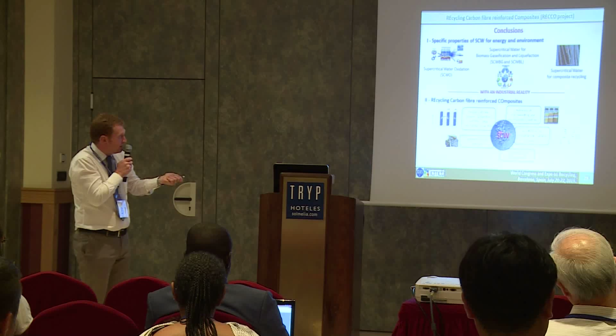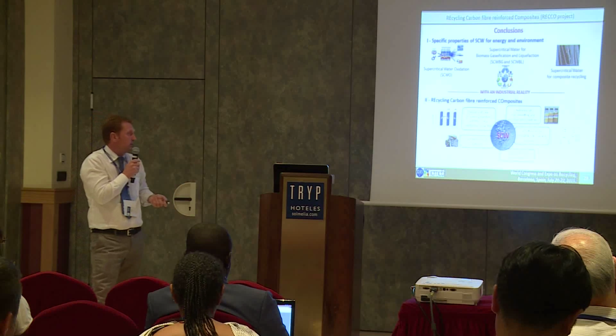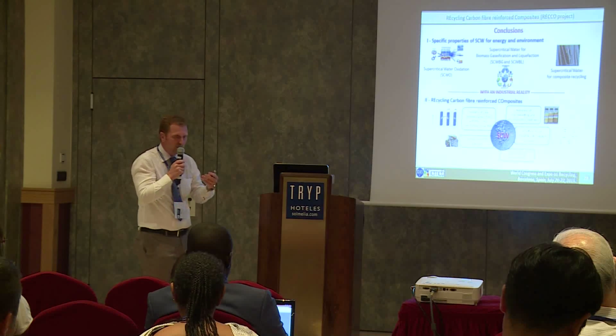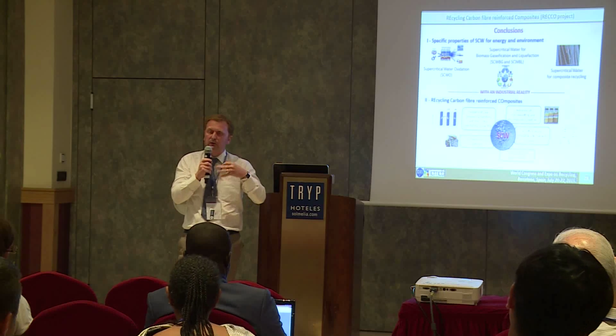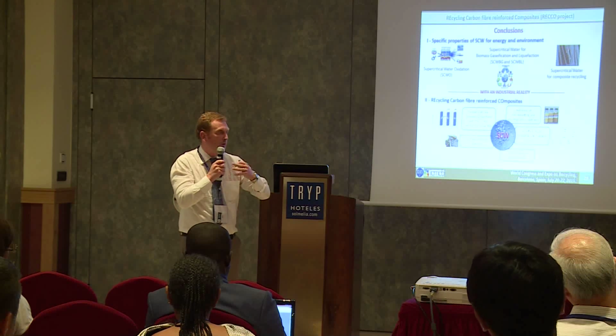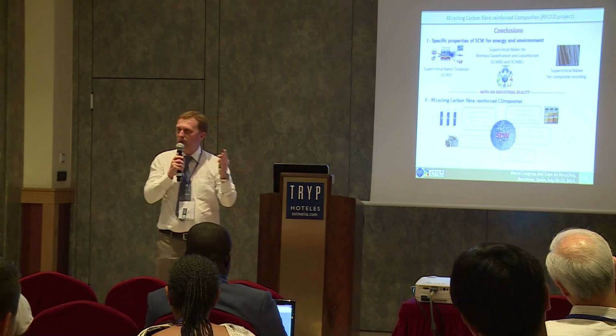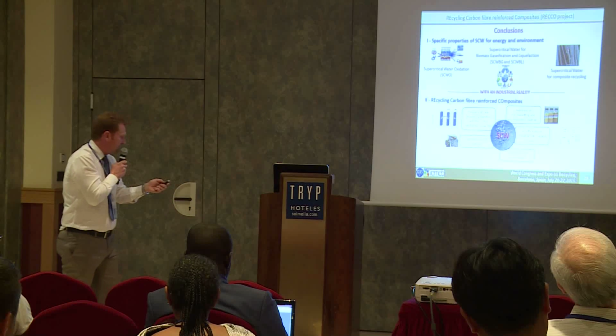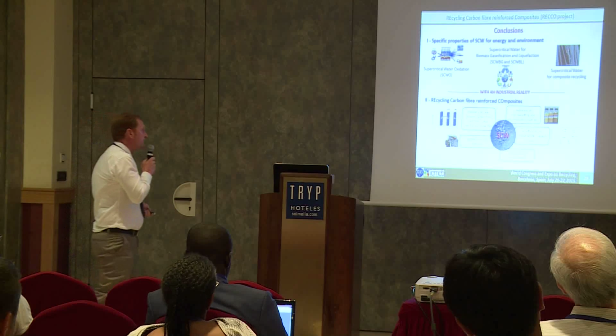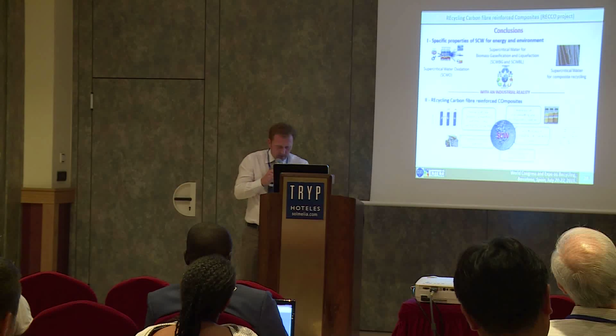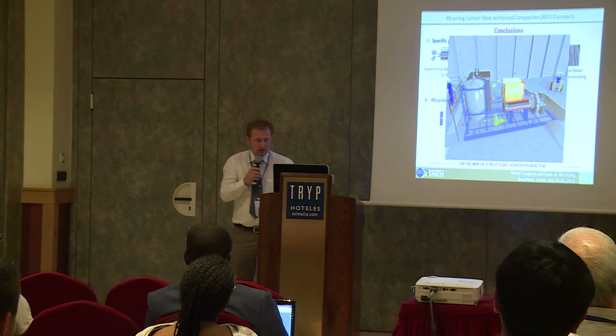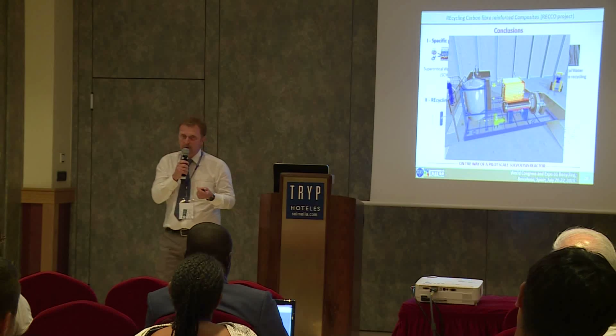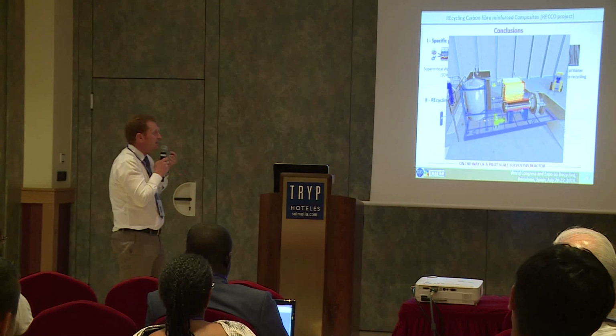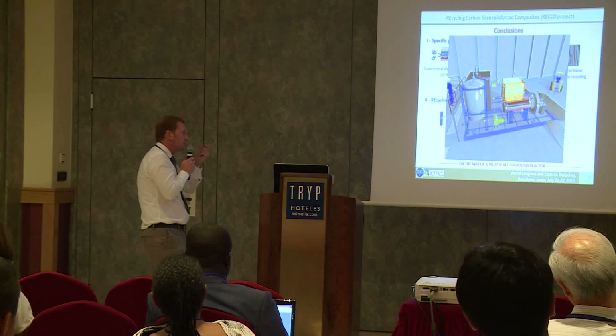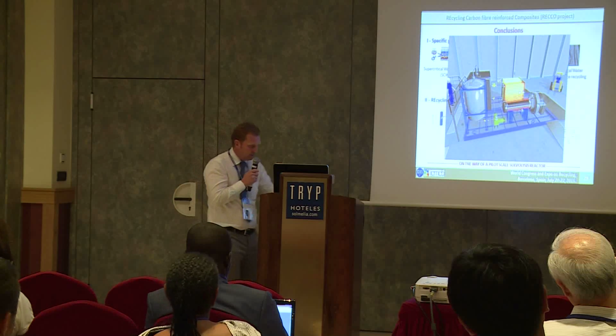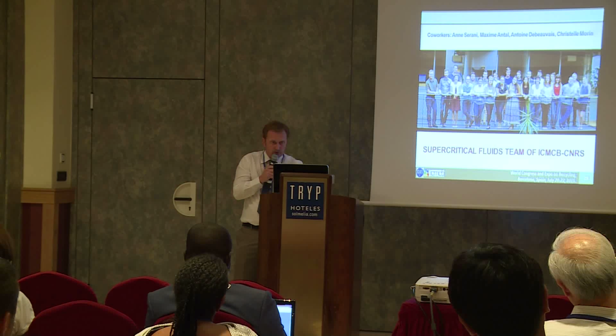An important point for me is the possibility of treatment of multi-materials. You can put in a composite which is stuck with steel, with different kinds of material, and at the end you will recover the steel, aluminum and so on, and the carbon fiber. And as was evaluated, a low impact on the environment. So now we are on the way to a pilot scale solvolysis reactor, and information is still missing, as I told you, on the market needs for reusing this kind of material.